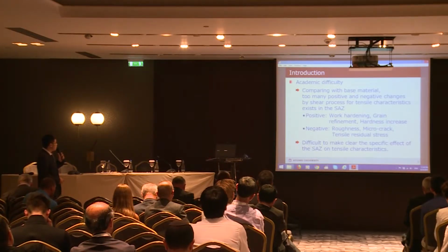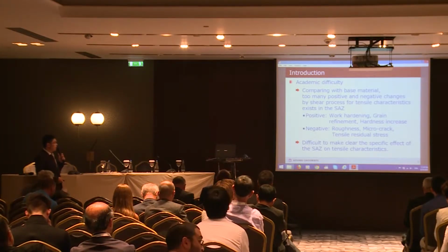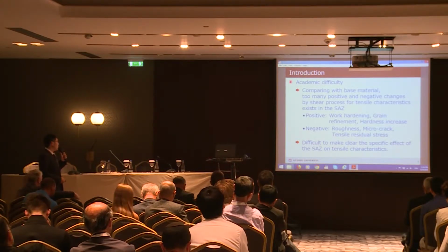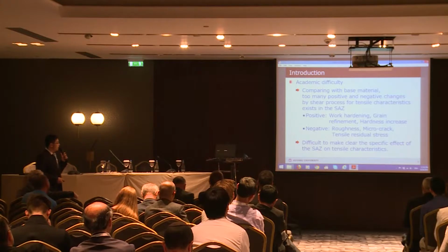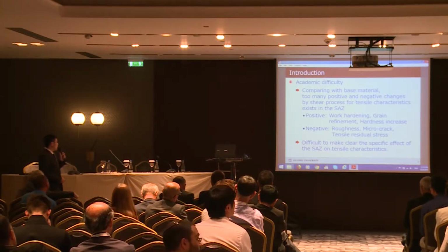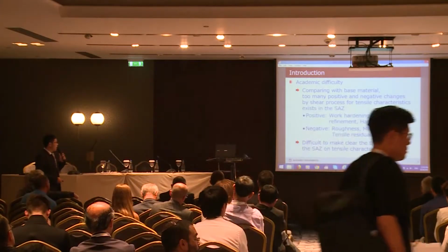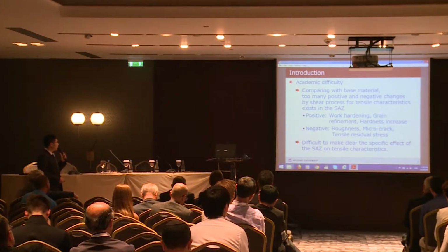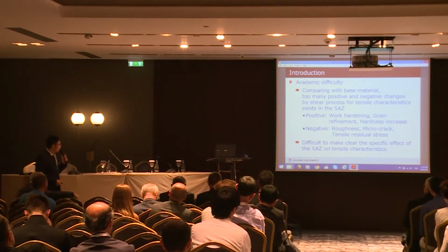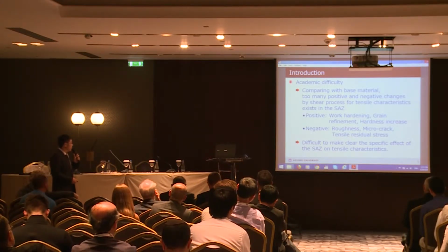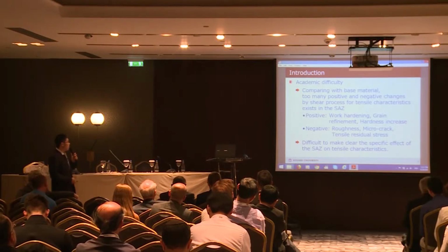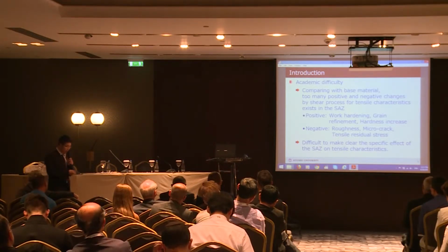Comparing with base material, many positive and negative changes in tensile characteristics due to the shear process exist in the SAZ, like work hardening, grain refinement, hardness increase, roughness, micro crack, and tensile residual stress. So it is difficult to make clear the specific effect of the SAZ on tensile characteristics.